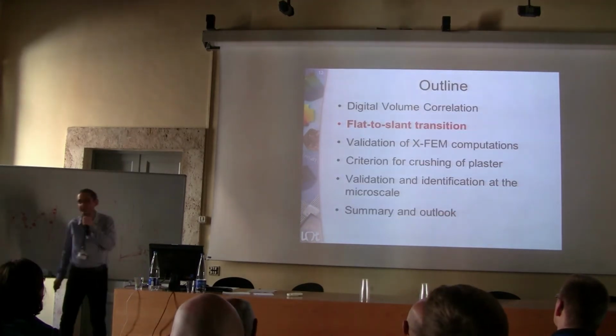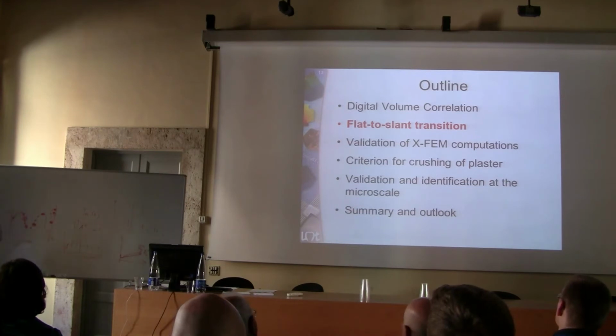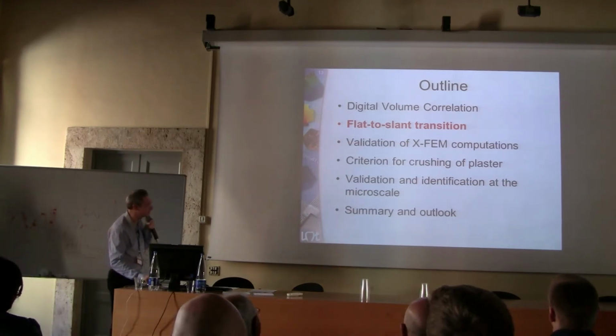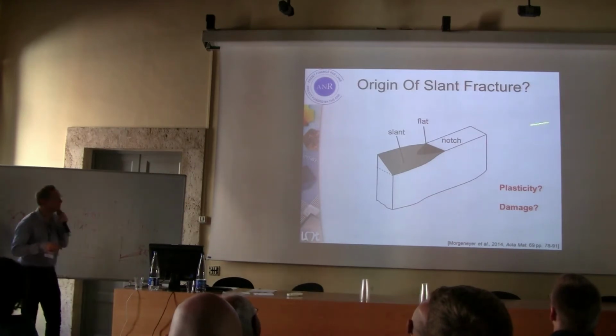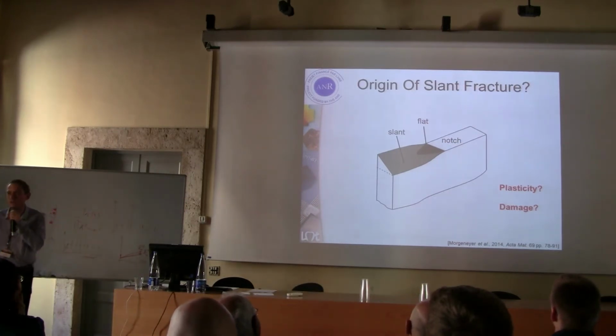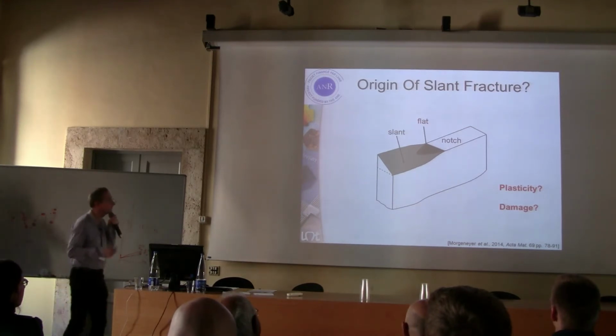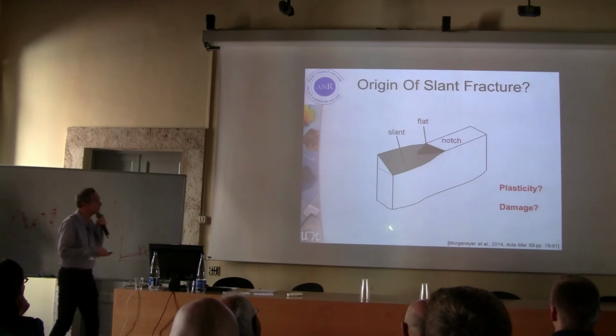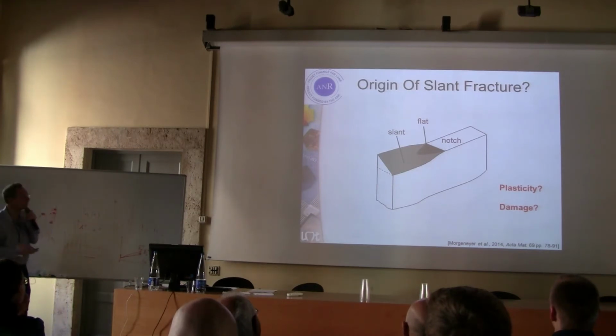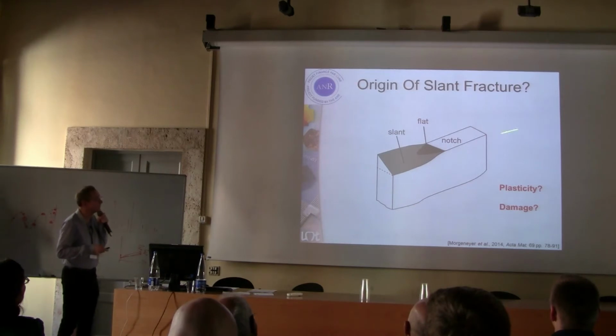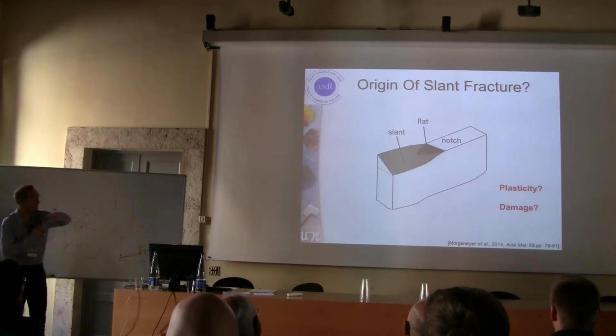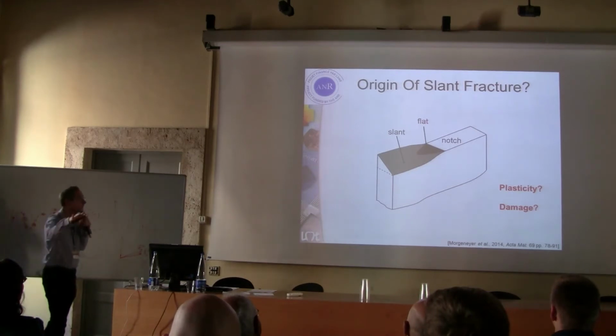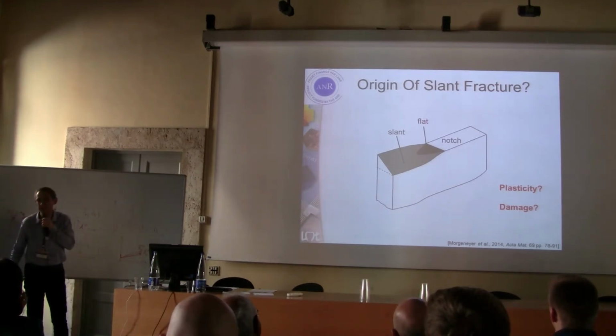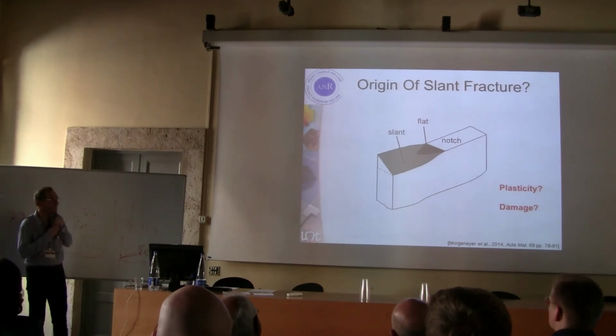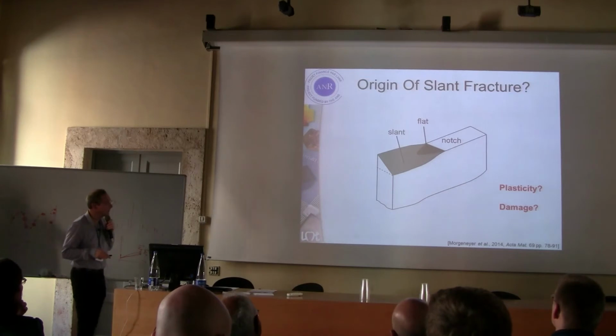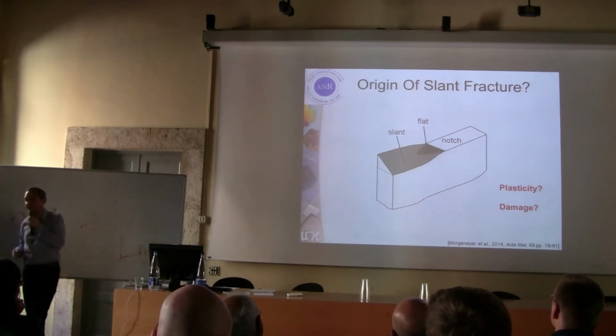That's the transition to the first illustration I'd like to comment on, which is to understand the so-called flat-to-slant transition. What do we mean? If you take a notch sample, for instance an aluminum alloy used in the aeronautics industry, and you just pull it in mode 1, the opening regime, what you see is that a crack initiates and starts to propagate in mode 1 condition. But very early on it tilts. This is something that's been known for some time. The question is, what is the driver behind this phenomenon?